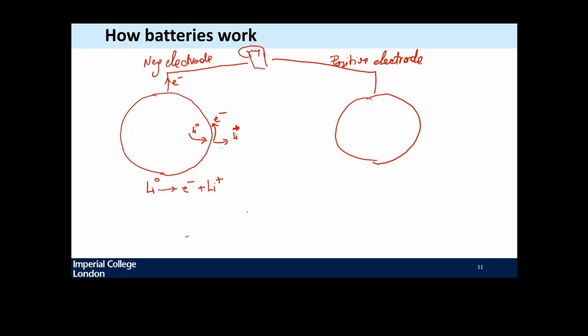At the same time, I have another material that was chosen because of its inclination in this electrolyte to capture an ion, collect an electron for electron neutrality, and do what we are calling an intercalation reaction, but it's an electrochemical reaction. So on this other side, I have that lithium plus one electron coming through some conductive medium inside the electrode, goes to Li0 inside the electrode.